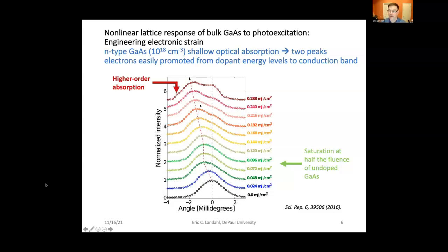The X-ray penetration depth is probing both the unstrained substrate as well as the area closer to the surface, which is undergoing some distortion. At the beginning, the peak simply shifts linearly, and then at some point, there's the onset of saturation, where tracing that diffraction peak on the left, that is the one that's changing due to charge carrier expansion, that comes on much earlier in the case of the doped gallium arsenide. And that would be because you expect electrons to be much more easily promoted from dopant levels to the conduction band. So effectively we tuned the saturation point by doping in this case.